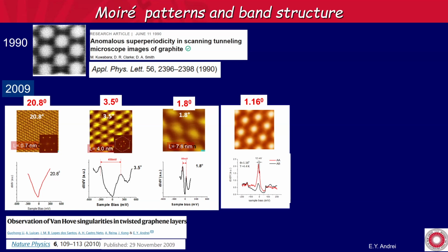Now, the reason we needed to suspend it is because at the time, the only way we could look at graphene was to put it on silicon dioxide, and the substrate is terrible. It has lots of dangling bonds. It really interferes with the band structure. So we had to suspend our samples to look at what's going on. So this is one of the things that we did. Since it's a TEM grid, we needed a huge sample, so we couldn't just do an exfoliated sample. We used CVD graphene.